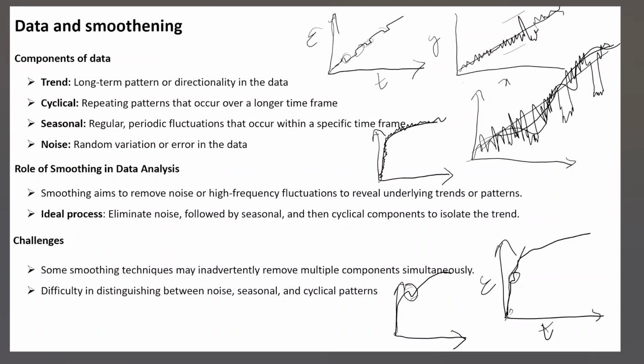If I smoothen too much, this may become like a normal ductile strain curve. In that case, this yield point phenomenon can be completely removed. So care should be taken to use a filtering technique which doesn't remove the principal component, the variation from the actual curves.